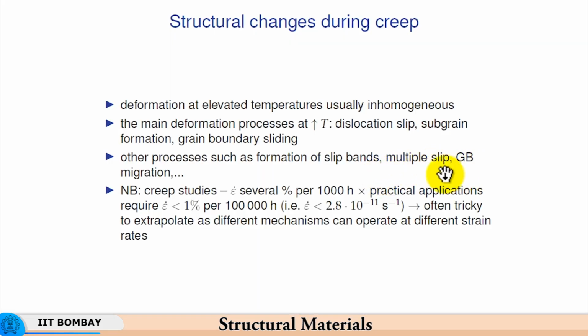So, formation of slip bands, multiple slip, grain boundary migration. These are also processes which depend upon the dislocation density of the material. For example, if the dislocation density is very high, then grain boundary migration can take place. If there is a big difference between the grain sizes, then bigger grains will grow further in size at the expense of the smaller grains. So, different kinds of processes resulting in change in the grain size would take place during the course of creep.